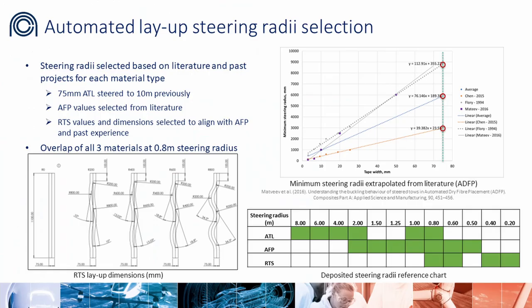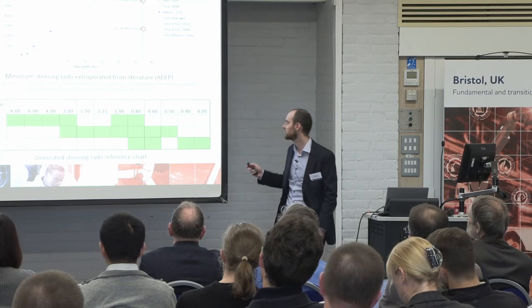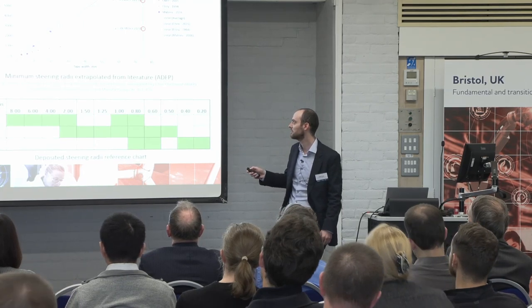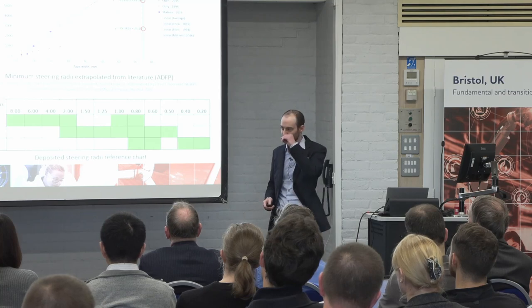And so very briefly, we wanted to set up our experimental design, if you like, and choose the radii we're going to use. And the process we chose was automated tape layup, which lays, in our case, 75 mm tapes, which are quite wide, and you typically wouldn't want to steer with that material at all, really. It's all geared for low cost and high rate. And so from literature, we had to extrapolate quite significantly to look at the possibilities of can we steer this material, which is going to be, as I say, 75 mil compared to below 10 mm, which would be typical for AFP.